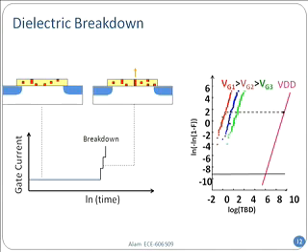50%. This is a log-log plot, so 50% will happen about there, and also the green is a little lower voltage. So you do it at 3 voltages, and you see they are all parallel. So if you want to say what will happen at 1 volt, then you will simply extrapolate to 1 volt and see what will happen.